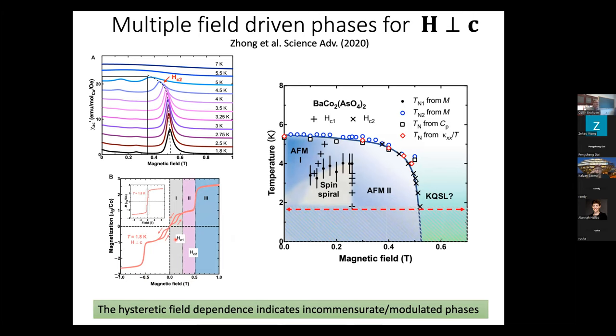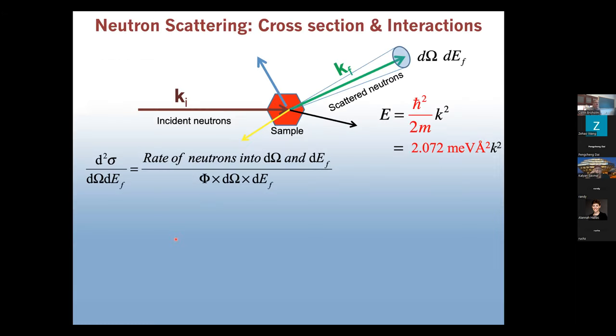And so to look for that kind of physics, to really study these modulated complicated magnetic structures, you really need something like neutron scattering to work that out. And so we'll be using neutrons, both to probe the static magnetic structure and the dynamic magnetic structure. And I like to remind students who might be on the call of some of the aspects of this technique. So it is a scattering technique, very much like X-ray scattering. We have an incident beam of neutrons, and we detect the probability of scattering from state Ki to state Kf. And we can transfer energy and momentum, and we'll be measuring the scattering probability, if you will, as a function of momentum and energy transfer.